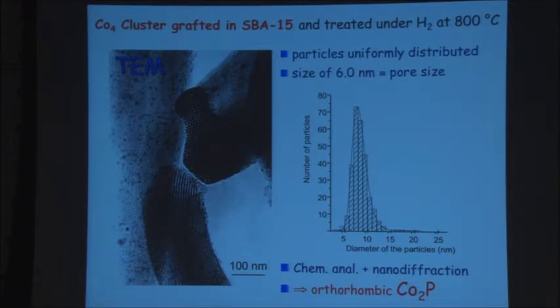The surprise was that we did not form cobalt nanoparticles, but instead cobalt phosphide, a Co2P phase. Of course, the phosphorus comes from the phosphine ligands. But that was intrinsically a surprise, but interesting.